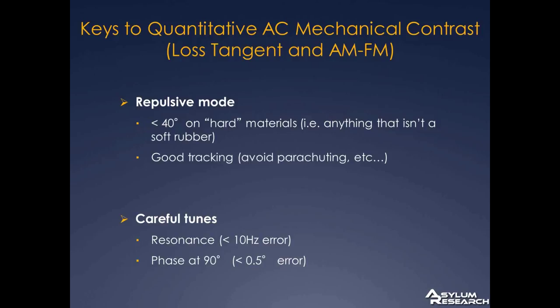What we've done is we've traded that kind of calibration for a tune calibration. We have to be on resonance, and we have to have our phase offset set so that at resonance you're at 90 degrees. And that is actually, in my experience at least, a heck of a lot easier to do than a reliable optical lever calibration.